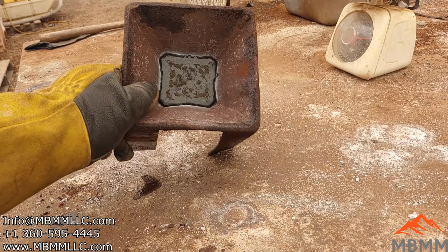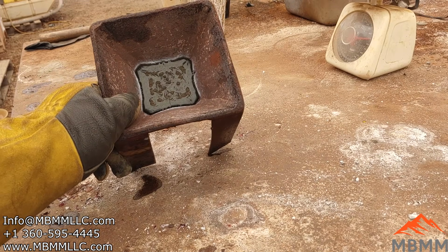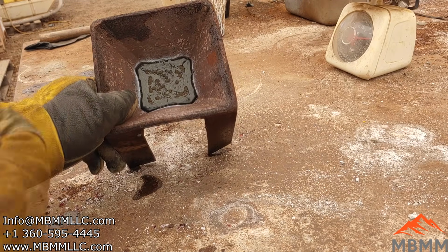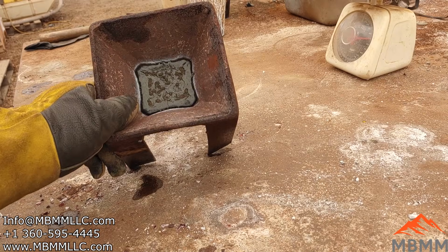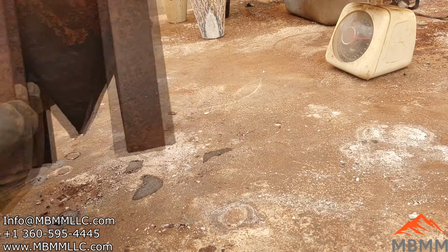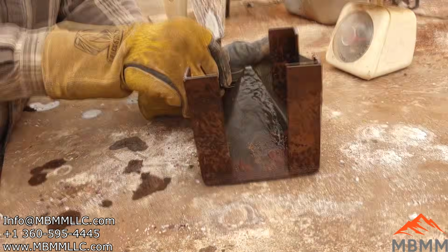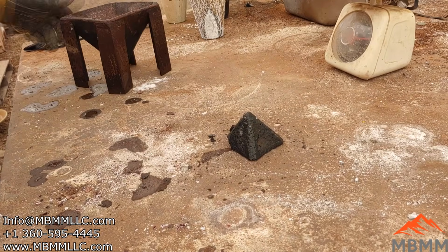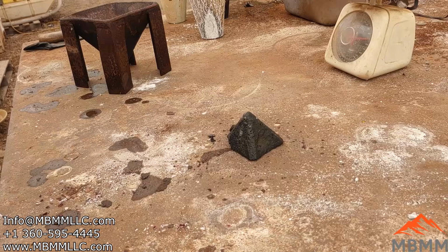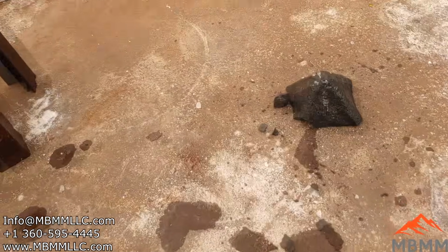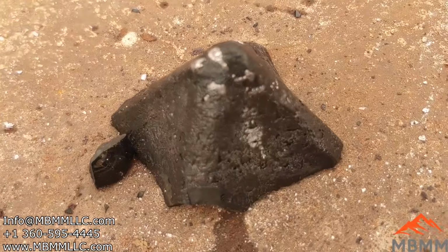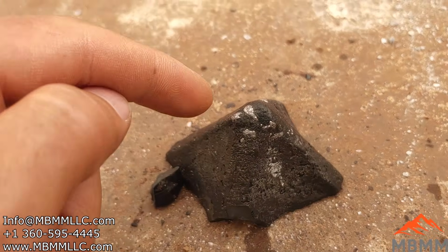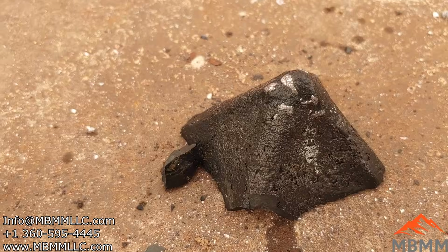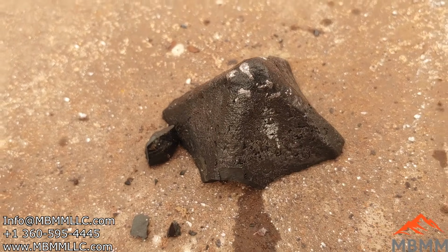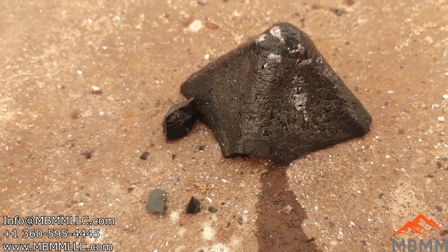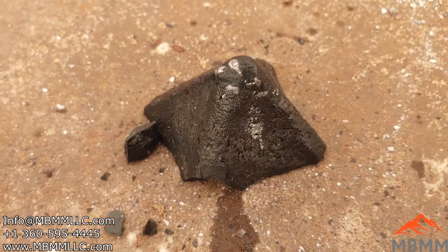Okay, here's our stuff, and if this worked right, and the flux recipe did its thing, and the iron did its thing, we should turn this over and we'll have a pyramid, and the top of the pyramid will be metal, and right underneath the metal will be slag. And there shouldn't be any matte, which will be a third layer in between. There's a lot of lead at the top there, so let me get a hammer and I'll just peck away at it and see what we got once I get it broken open.